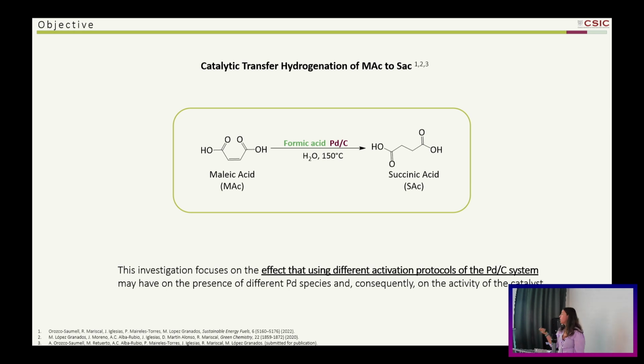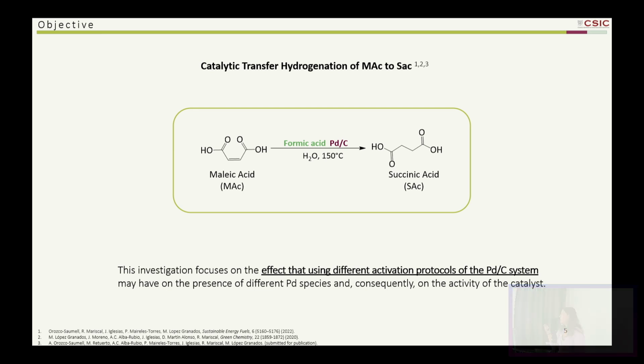In this work, we report the catalytic transfer hydrogenation of maleic acid to succinic acid using formic acid as source of hydrogen and palladium carbon as catalyst. And I'm focused on the effect that using different activation protocols of the palladium carbon system may have on the palladium species present in the catalyst and in the catalytic activity.